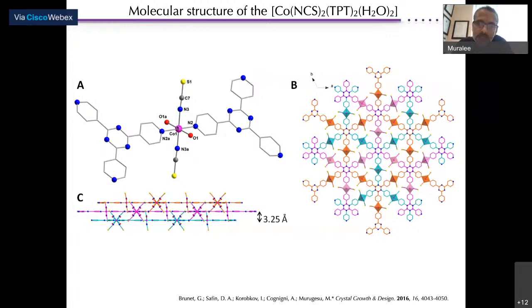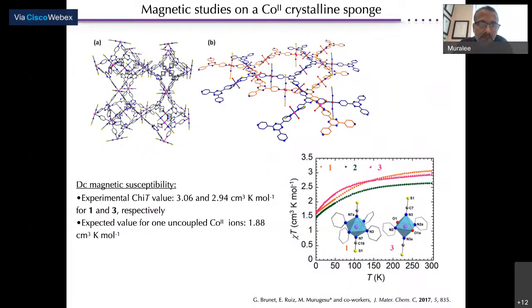The critical thing happening is while the methanol evaporates, some of these coordination sites are replaced in this framework. This leads to a transformation of the 3D framework to the 2D network here. Here is the side-by-side comparison of the 3D framework as well as the 2D network. And of course, it is a cobalt system. As we like to investigate the magnetic properties, you can see the coordination environment of each cobalt center is octahedral. Here, all of them are surrounded by the nitrogen atoms of the original framework. And this is a modified framework here, where two of these TPT ligands have been replaced by these oxygen atoms in this case.